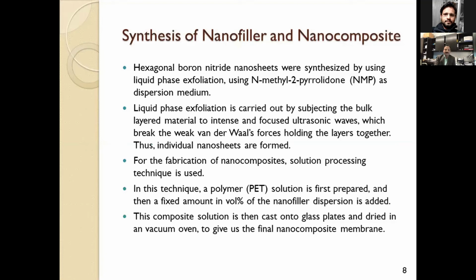And the second part is the synthesis of nanocomposites. Nanocomposites can be easily synthesized by a process known as solution processing, and solution processing is the method that we used. So first of all, we had the nanofiller solution. We combined it with a polymer solution, which we had formed, in which polyethylene terephthalate was dissolved into the same solvent as used for the nanofiller synthesis. Both of these solutions were combined, and the final solution was cast onto glass plates or petri dishes as we saw fit, and then finally the cast solution was dried and the nanocomposite was produced.